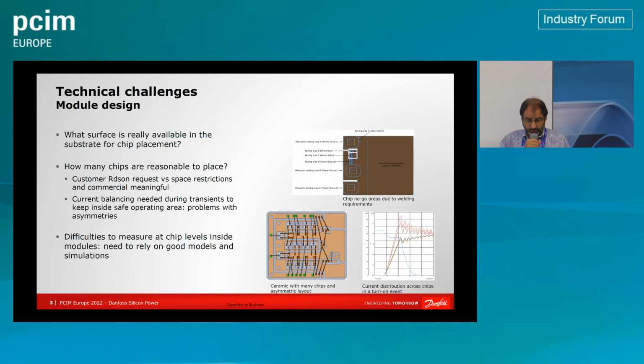The other important thing is also to make sure that you have current balancing between the different chips, especially during the transients, during the turn on and the turn off. So here I'm showing you an example of a module which has about 14 chips or more. What you can see on the picture on the right side is a simulation of the chips, and the problem is that because they have different local commutation loops and also gate loop inductances, the currents that some of the chips are seeing during a turn on, for example, are higher than the other ones. So it means that some chips are more stressed than other ones. And so the art of module production is to try to avoid that these things happen. So I'm putting that as an example of what you try not to get.